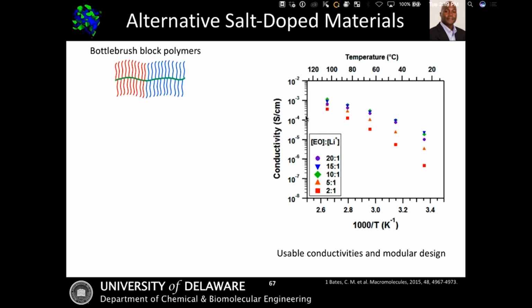So this data shown here on the right is just one example from the Grubbs group, where they were able to actually get conductivities up to about 10 to the -3, but more importantly, they were also able to use the system to suppress crystallization, especially at the higher salt loadings, so on the order of 10 to 1, 5 to 1, and 2 to 1. Additionally, one of the issues with these systems and one of the areas that can lead to further improvement is it's very hard to get things like network nanostructures from these systems, and so there's opportunity for actually designing new bottle brush polymers and other systems that actually have these co-continuous pathways.